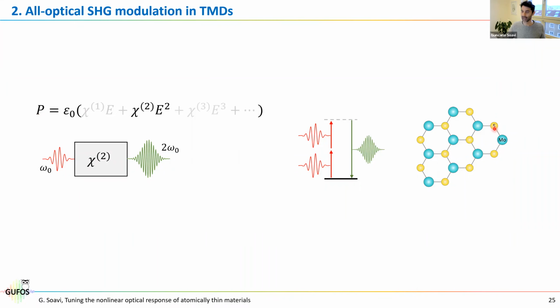Now the atoms in the hexagon are not the same anymore, so the material becomes non-centrosymmetric, and since the material is non-centrosymmetric, we can also have a second order response, so a chi2. So in these materials, we will be looking at second harmonic generation, which means we arrive with photons at h bar omega 0, and we generate photons at 2 h bar omega 0. So this is the same concept as before, but instead of having 3 incoming photons, we have only 2 incoming photons, and we have also this energy conservation.